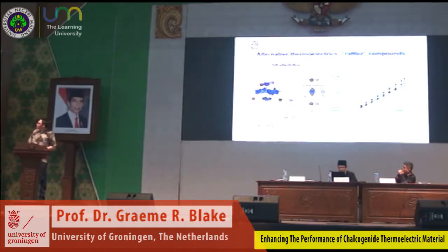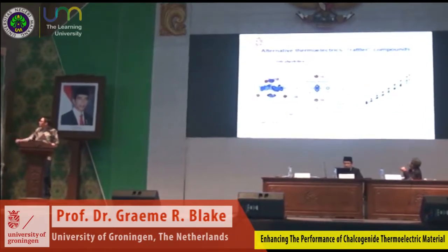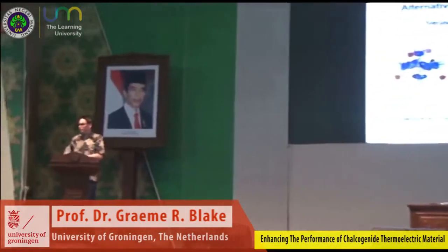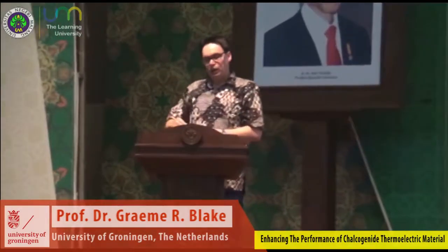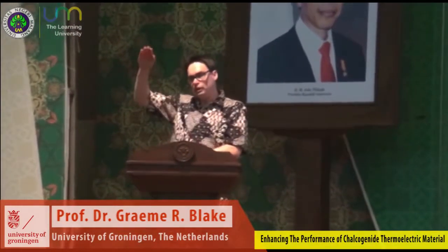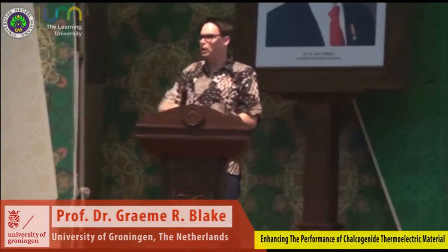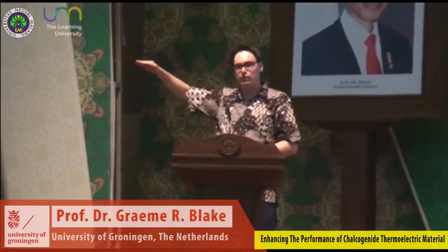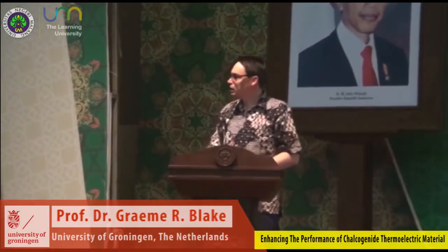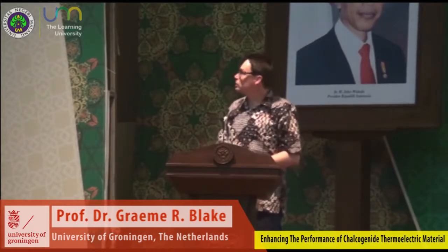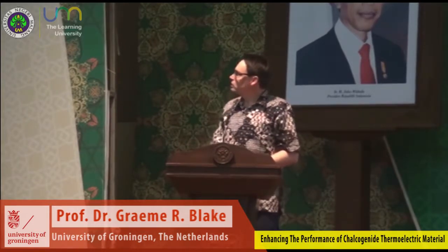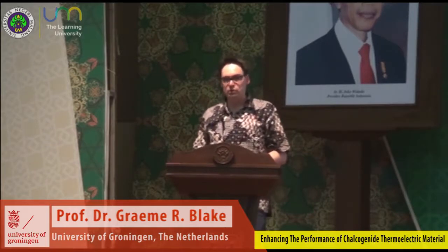Another similar material is the tetrahedrites. And here, although there are not really large voids, there are copper cations, which are shown in blue on the left-hand side, and they have a unique coordination by 3 sulfur anions. And these copper cations also are allowed to vibrate with a very large amplitude perpendicular to the plane of these CuS3 units. So again, this helps to scatter phonons. And these tetrahedrites, which are sulfides, are also achieving ZTs of around 0.7 in the latest results.